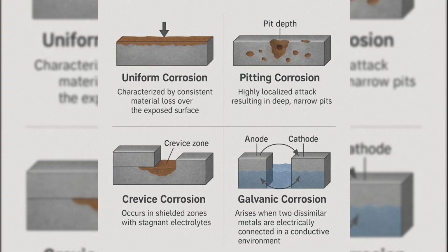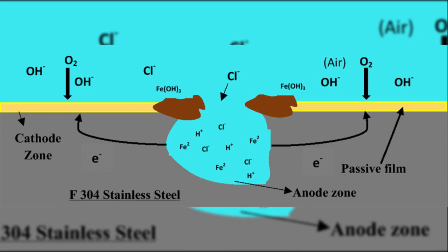The real risk begins with localized corrosion, especially pitting corrosion. In this case, the surface may look almost untouched, while tiny pits form at specific locations. These pits act as highly active anodic sites. Corrosion proceeds rapidly downward rather than outward, drilling deep into the metal. A pipe, tank, or structural element can fail suddenly, even though 99% of its surface appears intact.